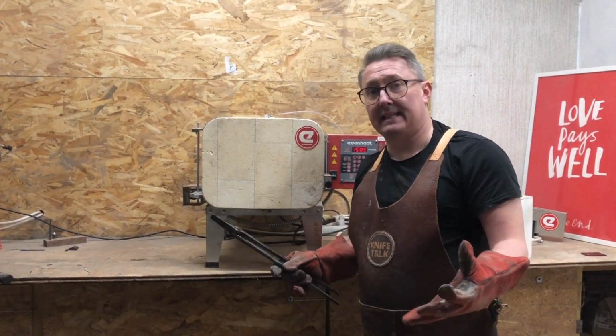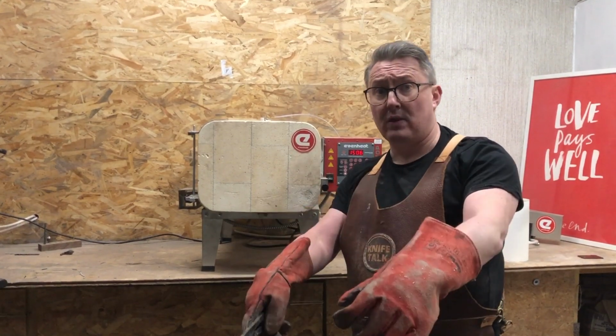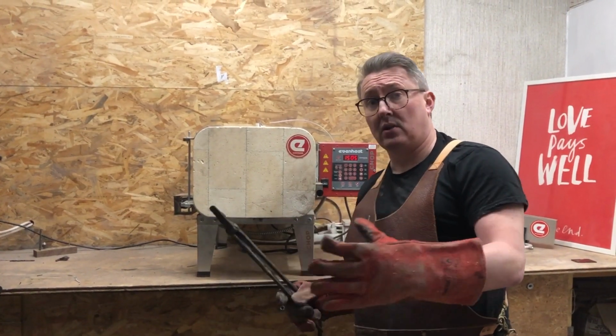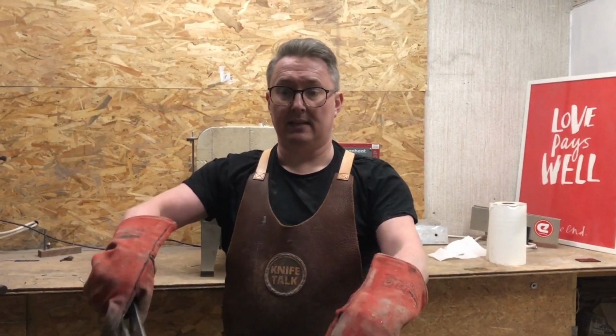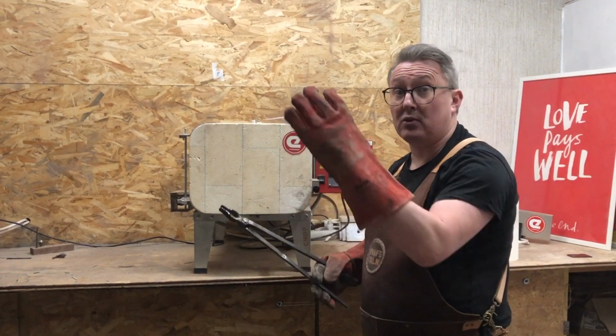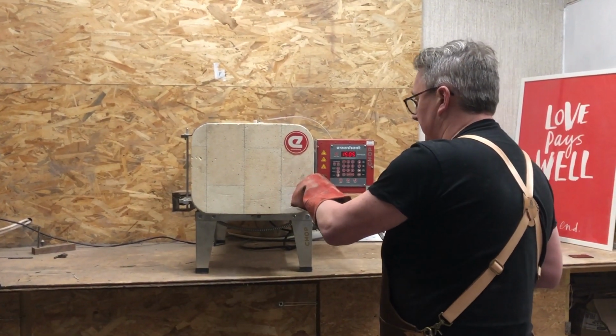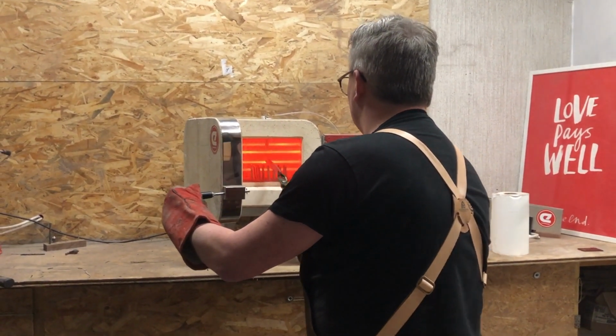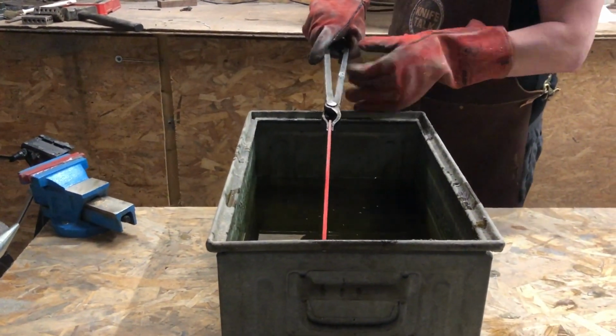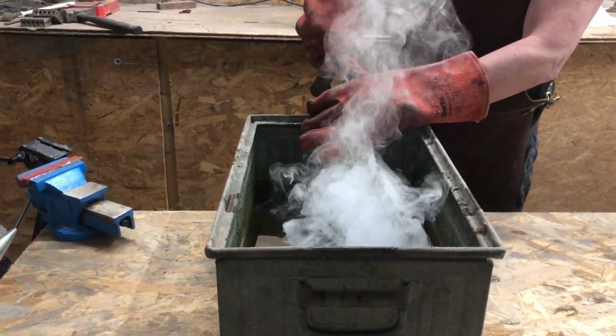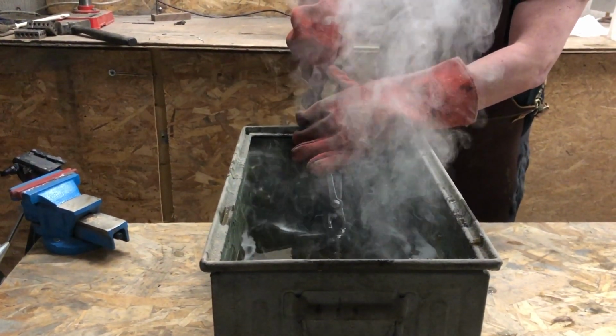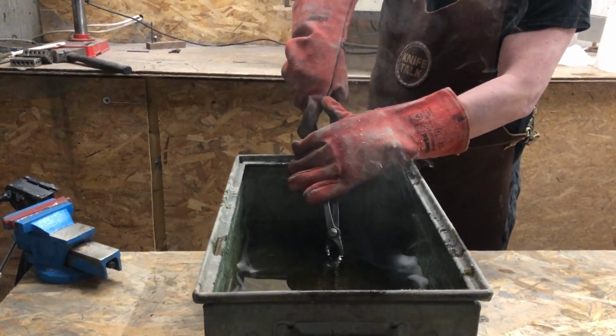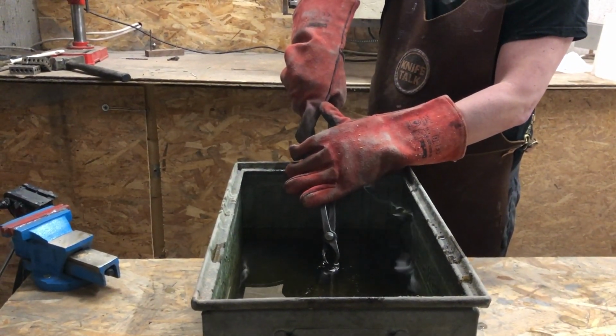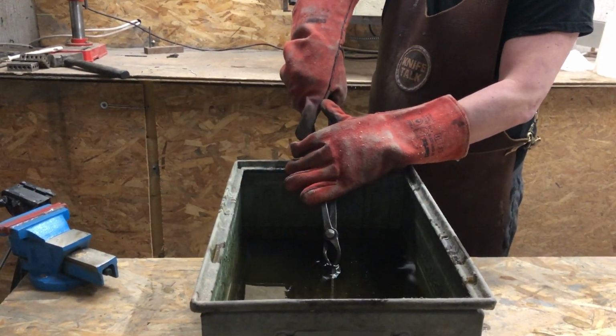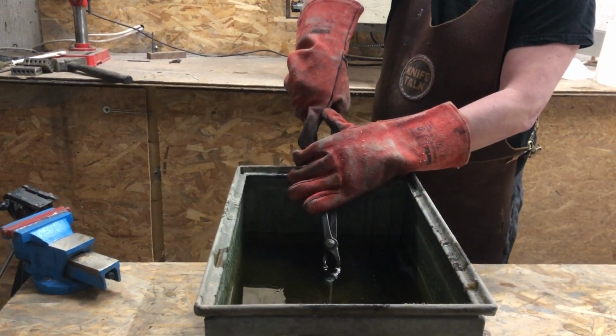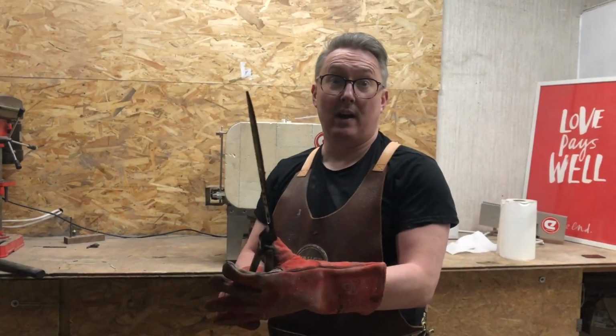So the blade's been held at 1510 for around about 15-20 minutes now. So I've got my oil ready, that's nice and warm. And what I'm going to do is in one solid motion, pick up the blade, bring it down straight into the quench tank. Okay, here it goes. Make sure you're wearing gloves for this. You just want to move it, just to move those bubbles from the surface of the steel. There we go. That's one hard blade.